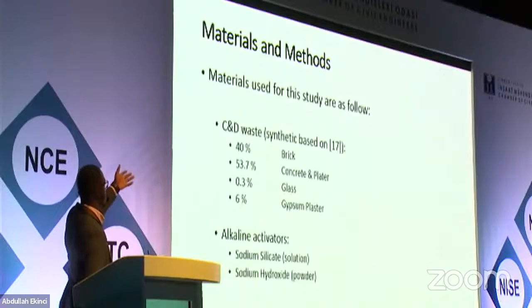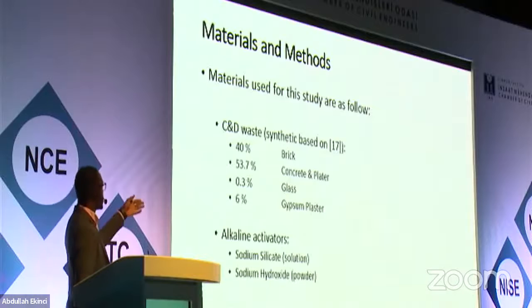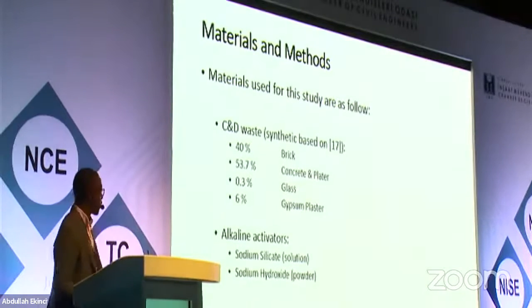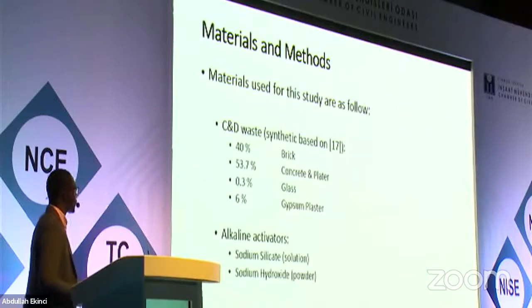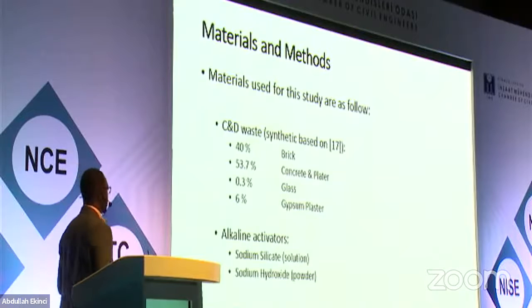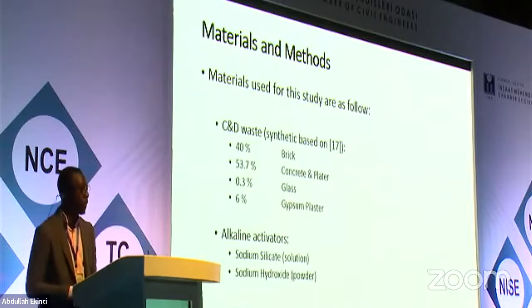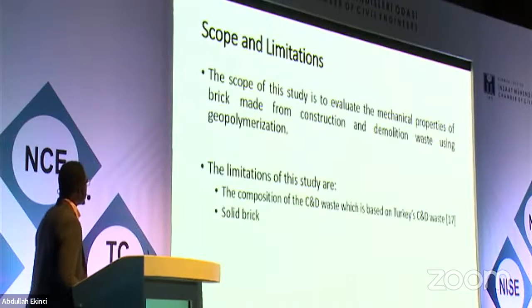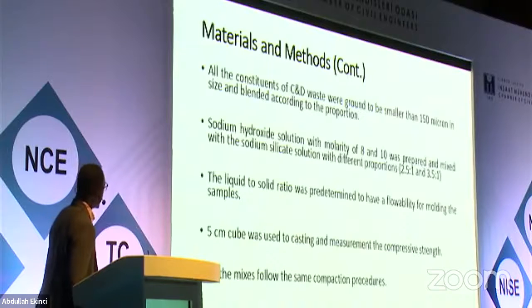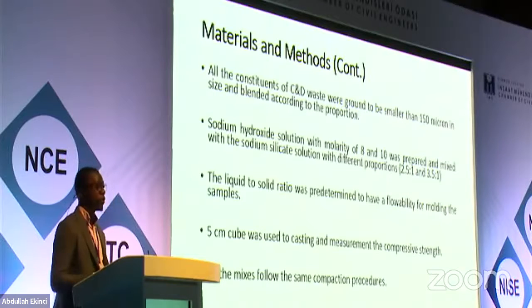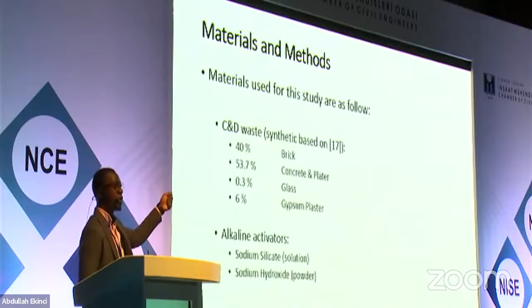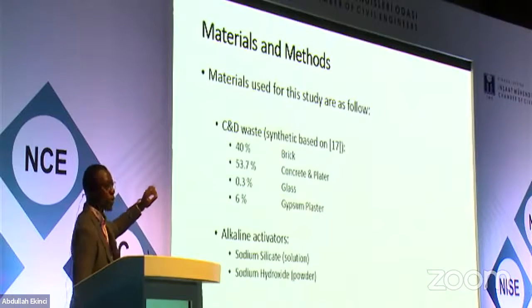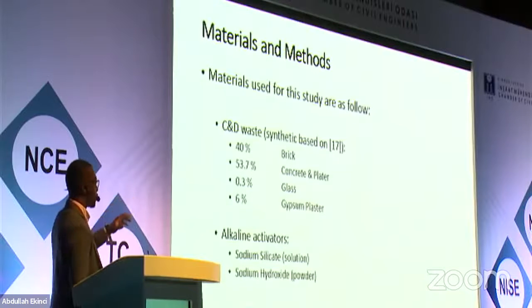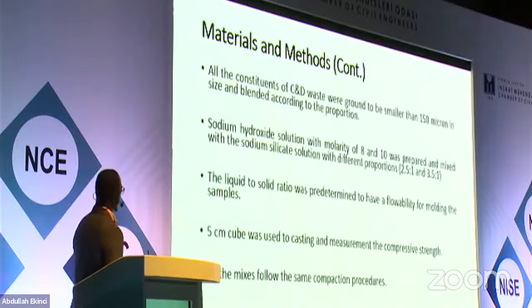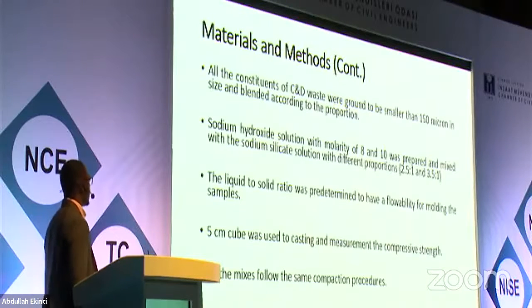Okay, those are the materials we used for our test. We use brick, concrete, glass, gypsum, and also water. As alkaline activators, we use sodium silicate and sodium hydroxide: sodium silicate as liquid and sodium hydroxide as powder. We took the brick and ground it up to 150 micron, and also concrete, glass, and gypsum. So the brick, we made it powder. And the liquid-solid ratio was determined to have workability for molding the sample.